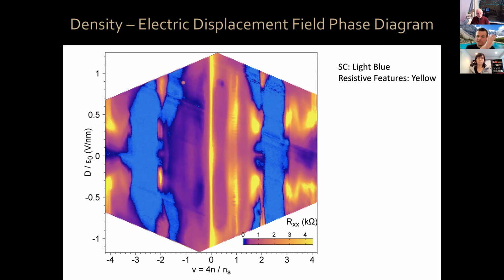Now, left and right. Now the situation is a bit more complex. You can focus on the symmetries. For example, indeed, superconductivity is mostly between 2 and 3 and -2, -3. Or you can focus on the asymmetries. For example, these bright yellow features are not as present and as pronounced here. So this is actually something quite similar to magic angle twisted bilayer graphene. With respect to charge neutrality, you have a certain degree of asymmetry in the system. Now because this is so complex, we can try to measure other quantities and see if they correlate with what we observed in this phase diagram.